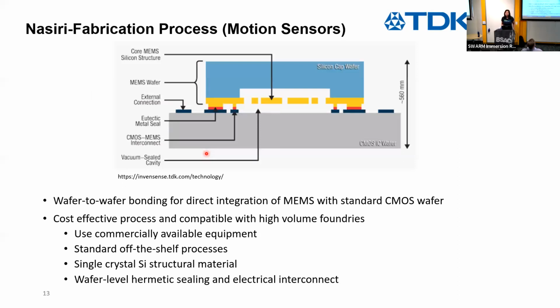One of the core patents for InvenSense was the Nasiri series fabrication process. This is the process that we use for motion sensors. It uses wafer-to-wafer bonding so that we can do direct integration of MEMS to CMOS. In the image here, you actually see 3 different wafers. The top one, the blue one, is the silicon cap wafer. In the middle, the yellow color, including the red, is the core MEMS wafer. That's where we define the structure for the accelerometer and gyroscope. And then the gray wafer at the bottom is the CMOS wafer with all the circuits.